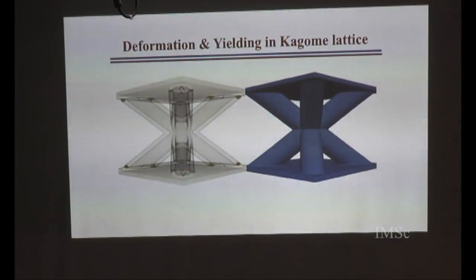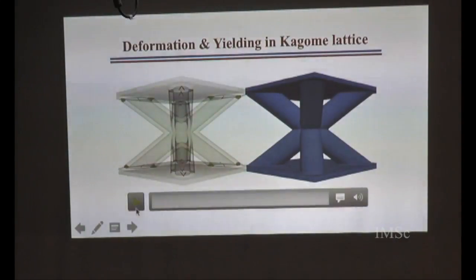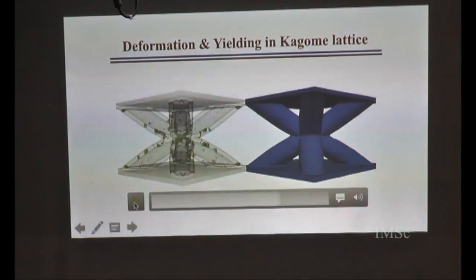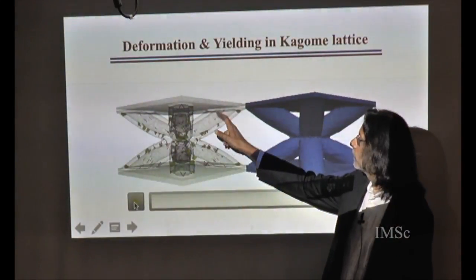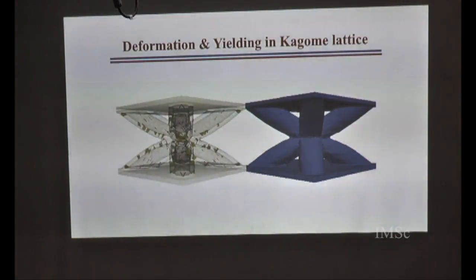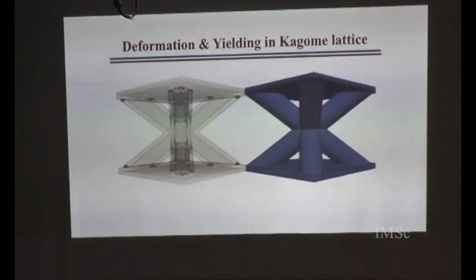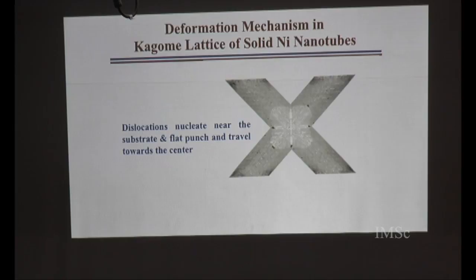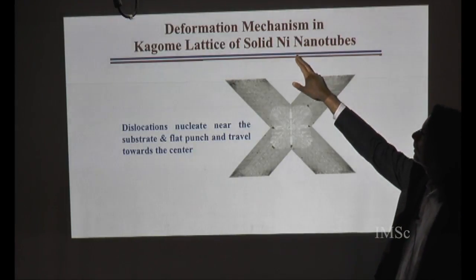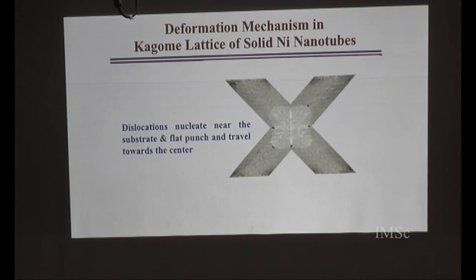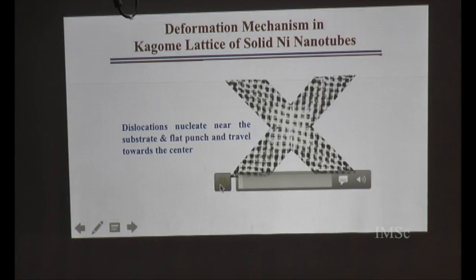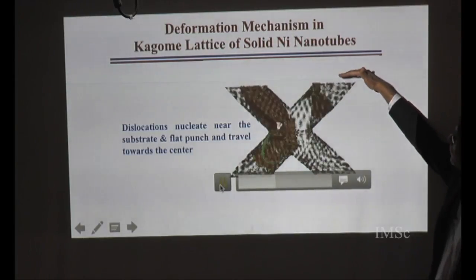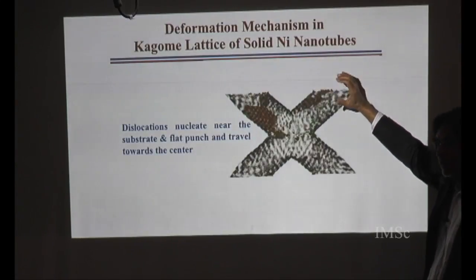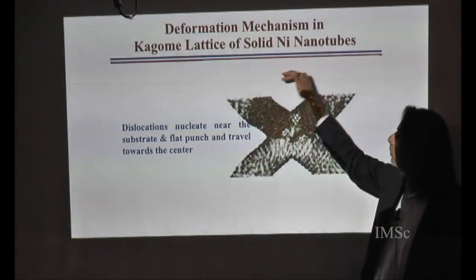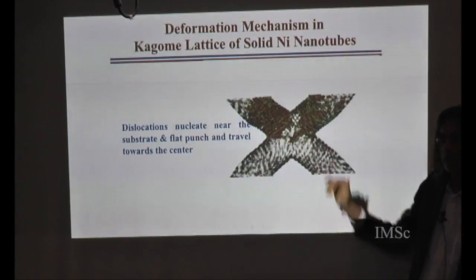So this is a movie. I'll show you the deformation in flat punch and how the system responds. This is one flat punch experiment, and then I will describe the two kinds of lattices we have. First, the Kagome lattice of nickel nanotubes which are solid. In this movie, dislocations are formed in the system, but the dislocations are coming from the flat punch and Kagome structure interface and also from the substrate. The dislocations nucleate at the boundaries and then travel to the midpoint. So that's one.